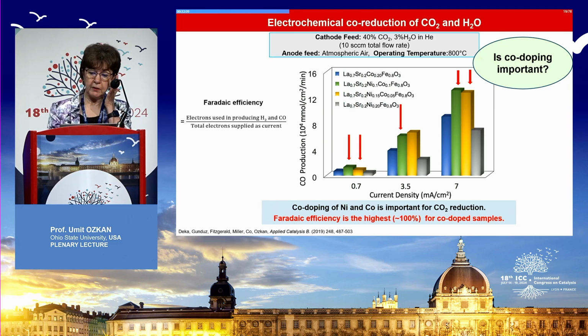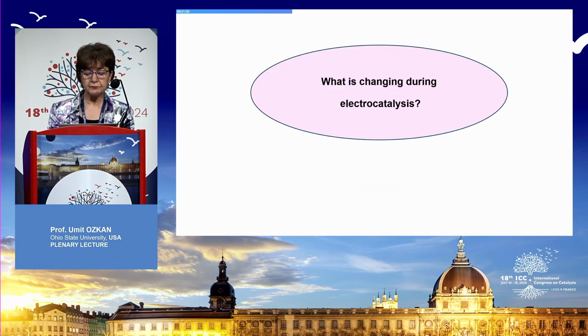Is co-doping important? And the answer is yes. The best CO production rate, for example, is achieved when we have both nickel and cobalt doping. Also, the best Faradaic efficiencies are obtained with the co-doped samples.